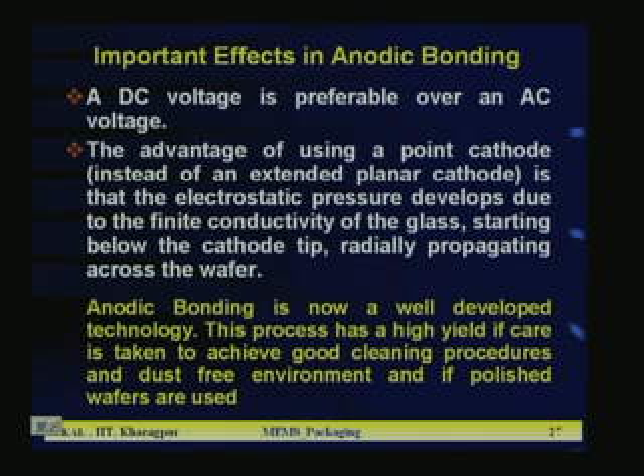Now, what are the important effects in anodic bonding? There a DC voltage is preferable over an AC voltage. The advantage of using a point cathode, I mentioned a few minutes back, you require a point cathode. Why? Because in that case electrostatic pressure develops due to the finite conductivity of the glass starting below the cathode tip, and it radially propagates along the wafer. That is the beauty of the point contact cathode. So, anodic bonding is now a well developed technology. This process has a high yield if care is taken to achieve good cleaning procedures and a dust free environment, and if polished wafers are used.